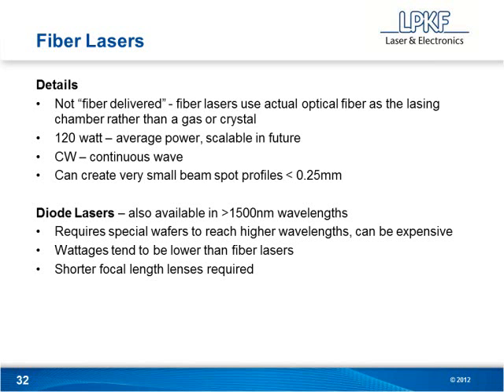But yes, the laser beam is actually generated within the fiber itself. The resonator is created by forming 2 mirrors actually in the glass itself, by writing fiber Bragg gratings into the fiber, and then the fiber is clad and the pump diodes are connected into the fiber and totally hermetically sealed. So no free space optics at all, and hence no possibility for contamination. It's very much the new technology within the laser industry, and this is simply an extension of that into new application areas. Changing the wavelength is simply using a different rare earth dopant in the fiber.